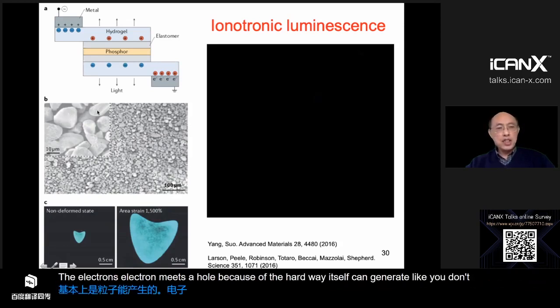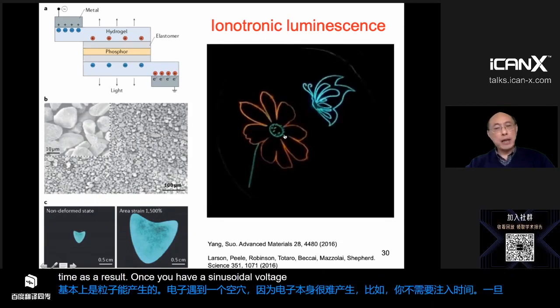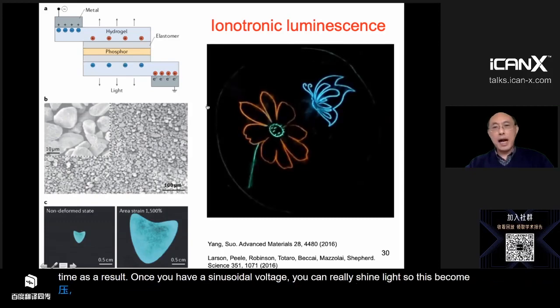Now, what we do is having this phosphor ceramic particle glued in between two elastomer layers. And then we apply voltage through hydrogel. We do not inject electron, right? It's ionic and there's an insulator. But we can apply voltage. As long as the voltage is sinusoidal, essentially the particle can generate an electron. Electron meets the hole because the particle itself can generate electron. You don't need to inject electron. As a result, once you have a sinusoidal voltage, you can really shine light. So this becomes an ionotronic device.